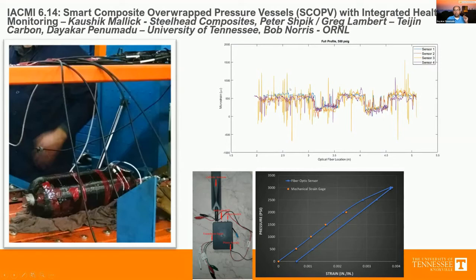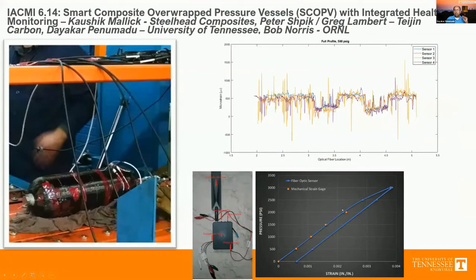And this is an important aspect to consider, especially with fatigue. If we have 10 or 30,000 cycles of fill and unfill type fatigue loading, these spikes in strain, corresponding to stress spikes, could actually reduce the fatigue life of the tanks much more than what you would predict if you just design based on fatigue tests, assuming the strains and corresponding stresses that are averaged over a foil region, which could miss all these singularities. This is an example of average strains compared to mechanical versus fiber optic strain.